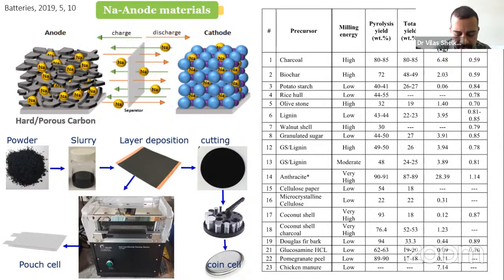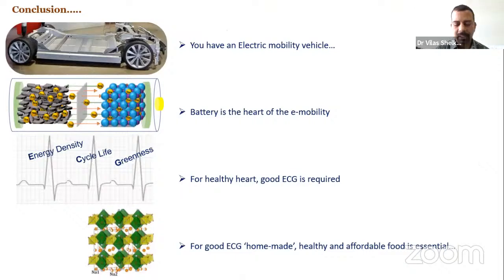But of course, these processes are done in a vacuum or inside a glove box, because the material which you use as the electrolyte cannot be exposed to environmental conditions. This has to be done particularly when you put the electrolyte inside and seal the pouch cell, so that process has to be done under vacuum or inert atmosphere. Then you connect the tabs to connectors for the electric supply, and then your battery is ready. So in this entire process, the main focus is on development of materials on the cathode side and anode side. To allow you sufficient time for your questions and answers, I will conclude the session.